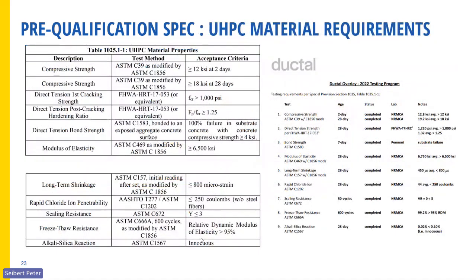Then the other thing, pre-qualification is required. The supplier had to provide pre-testing to make sure that the material could meet the requirements for strength, which was 12 KSI after 2 days, 18 after 28 days, and they also had to provide direct tension testing, bond testing, modulus of elasticity. So at the end of the day, the supplier has to provide a whole complete package showing that the material meets the specifications for the project.